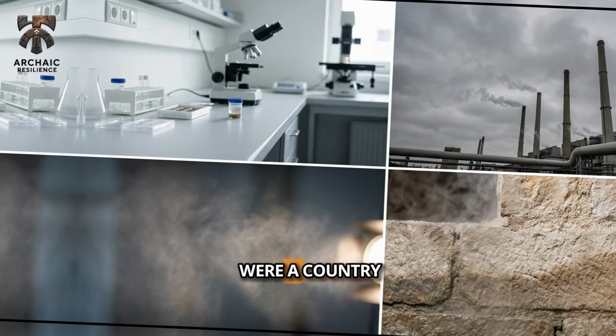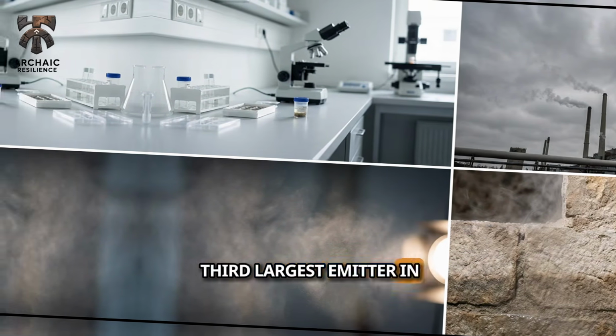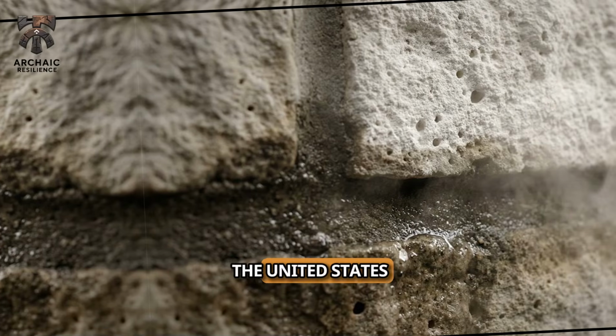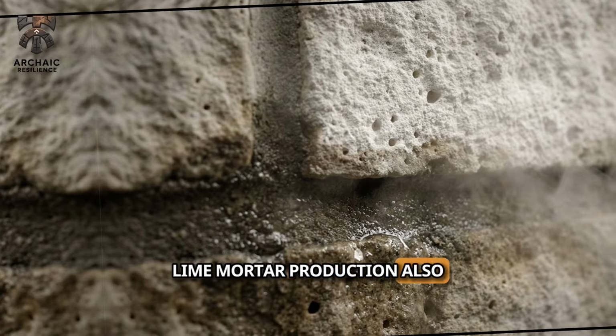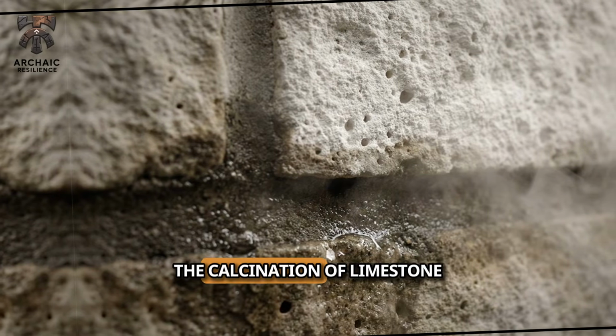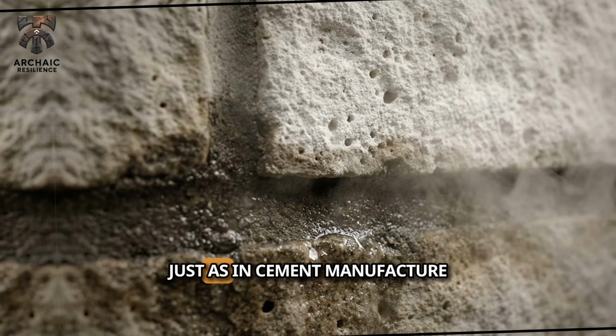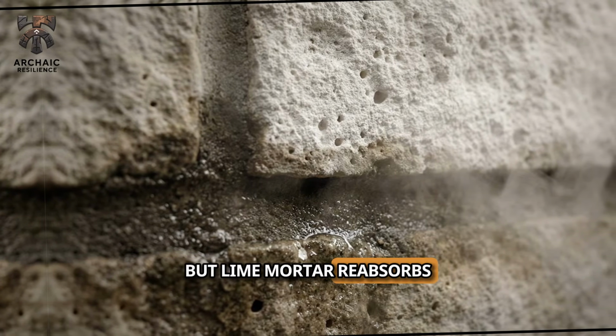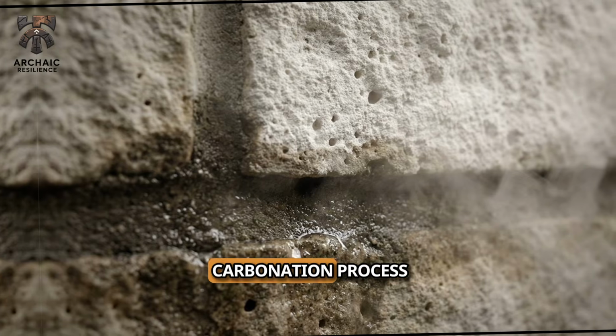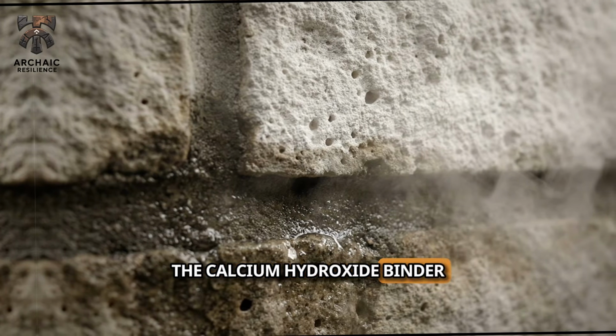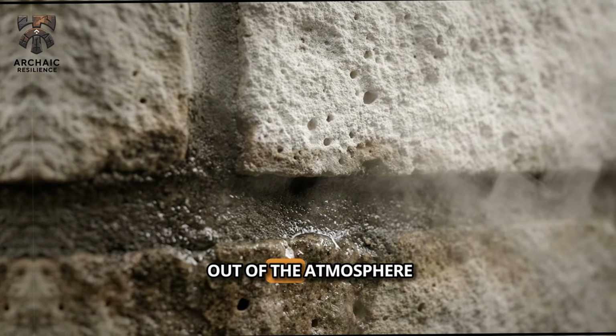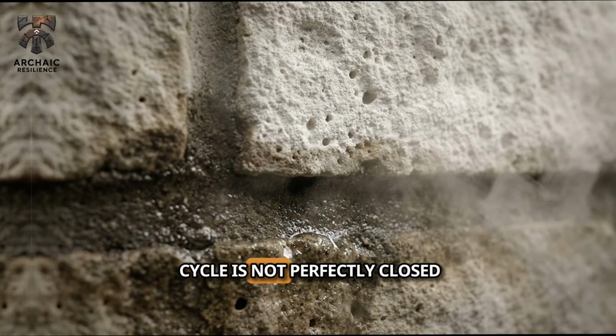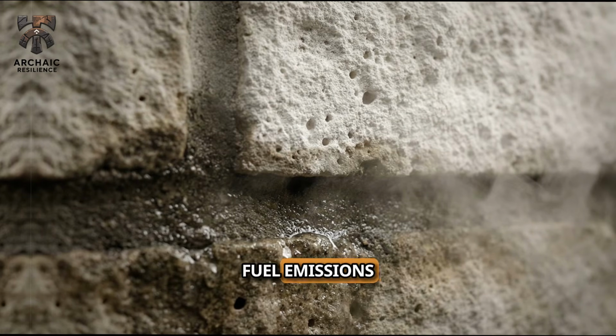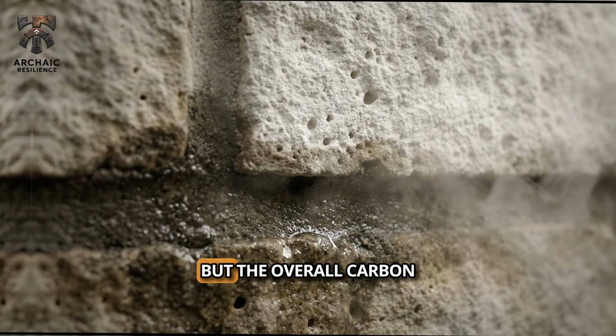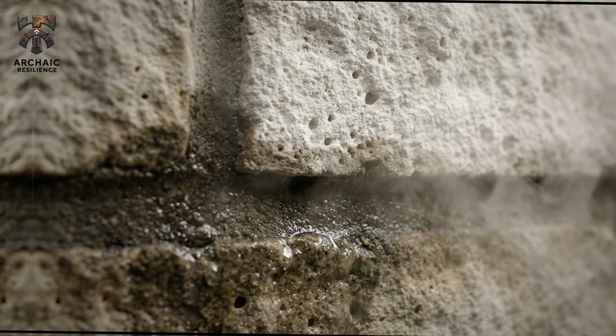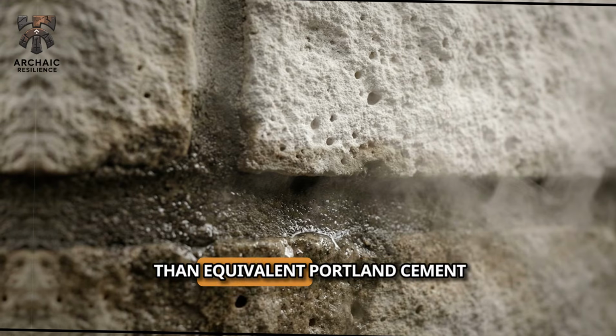If the cement industry were a country, it would be the third largest emitter in the world, behind only China and the United States. Lime mortar production also releases carbon dioxide. The calcination of limestone drives off CO2 just as in cement manufacture. But lime mortar reabsorbs that carbon during its decades-long carbonation process. The calcium hydroxide binder literally pulls carbon dioxide back out of the atmosphere as it cures. The cycle is not perfectly closed. Fuel emissions during lime burning represent a net addition, but the overall carbon footprint of lime mortar is roughly 60% lower than equivalent Portland cement.